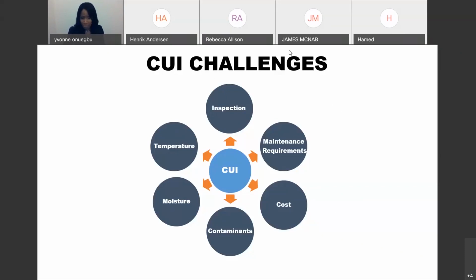Also, CUI is a complex system. We're looking at a lot of contributing factors: your water ingress, your temperature, your design. And most of these environmental factors are actually impossible to control. Your cumulative wetting is unpredictable, and because it's unpredictable, it impacts on the coating life and on the remnant life of the equipment. And then CUI can be very localized and it can occur anywhere. The picture that I've attached to this slide is CUI on a pipework that is located in an internal, enclosed module. This pipework is located in the roof, but when insulation was removed, we had CUI.